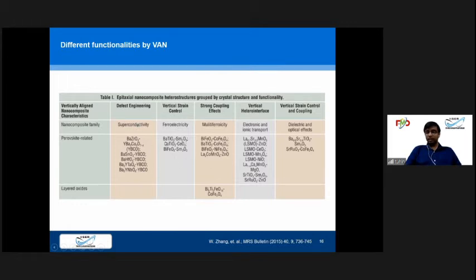This is an ABO3 structure. So if we are choosing that as a column, then we have to take a complex or non-symmetric structure to make a matrix. So this is another parameter we also need to consider. So let's summarize the considerations. First, we need to consider the lattice parameter of the substrate as well as the material we want to deposit. They have to be close to each other. Then we need to choose the matrix material and column material. Both of their structures cannot be similar. Otherwise, they will start mixing together and we will not get a matrix and a column. So these are the two main parameters we need to consider.